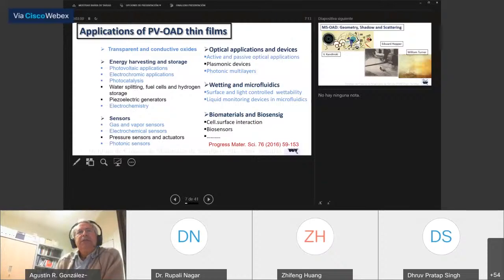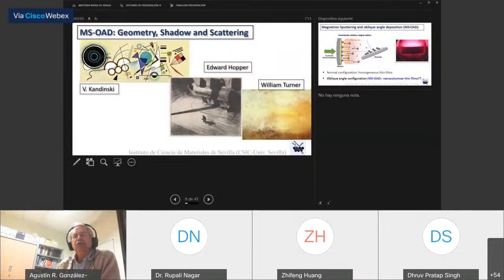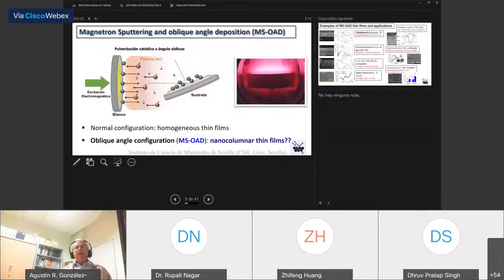But my point in this presentation is different. What happens if, in addition to the geometry and the shadow, we incorporate another principle for modifying the growing process, scattering? What happens if we incorporate some kind of mist, as in this painting by William Turner? In other words, what happens if we proceed in a magnetron sputtering facility where, besides controlling the tilting angle of the deposition, we have something very characteristic of this technique, which is the fact that we have gas between the target and the substrate?